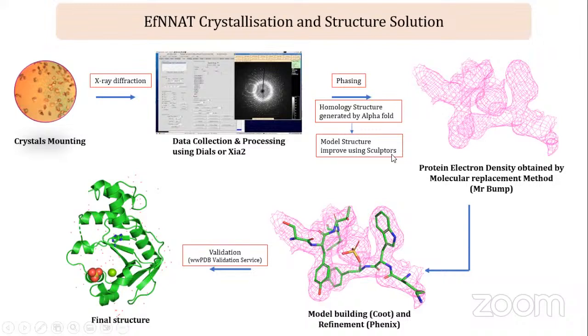MrBump in CCP4, and then a homology structure generated by AlphaFold was used as a search model, and we were able to determine the structure. Before it was used as a search model for the EF NaMNAT structure, the model was improved using Sculptor in Phaser. Several rounds of refinement were then performed, including addition of solvents using Coot and Phoenix. We were finally able to refine the structure, and then the structure was validated and deposited in the protein data bank.